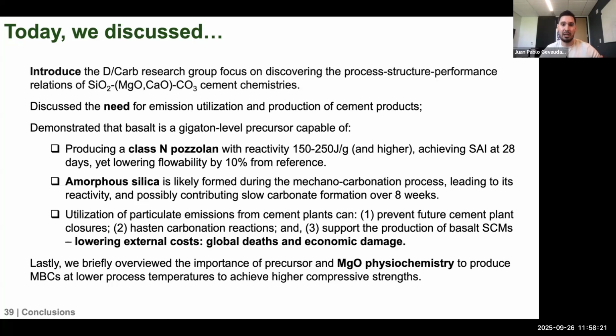I demonstrated basalt as a really key gigaton-level precursor available for us here in the US and other parts of the world, and the ability to produce a calcined product with somewhat okay reactivity, on par with fly ash. And of course, we're working to improve that even further. It achieves decent strength activity index, but really the challenge there is the water demand. And we think that water demand is really driven by the amorphous silica, the structure of that amorphous silica that is being produced and how it's creating agglomerates through the gelation process that we discussed today.